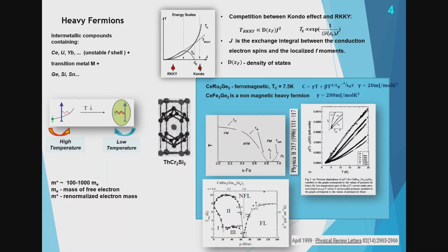And here is the transition temperature, and here is the quantum critical point. So the quantum critical point occurs at very low temperature when the thermal fluctuations are neglected, okay? This is my system here. It's a ferromagnetic system below 7.5 K, and it has a gamma which is not very big. It's not a heavy fermion, actually, but it's a bit higher than for normal metals already.